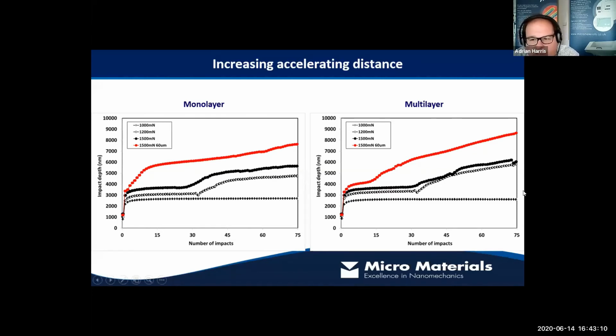The conclusion being that the nano multi-layer coating survives longer than the monolayer counterparts. There are some small negative depth steps, as we saw. You see just here it goes down slightly, and these are usually associated with initial cracking events and things taking place in the substrate. As time goes on, we're investigating what causes these behaviors more and more by using focused ion beam and cutting down through the impact sites to see what's going on inside the sample.